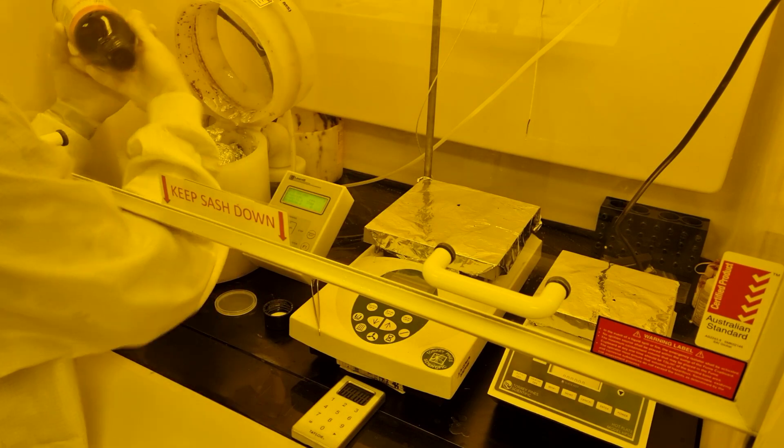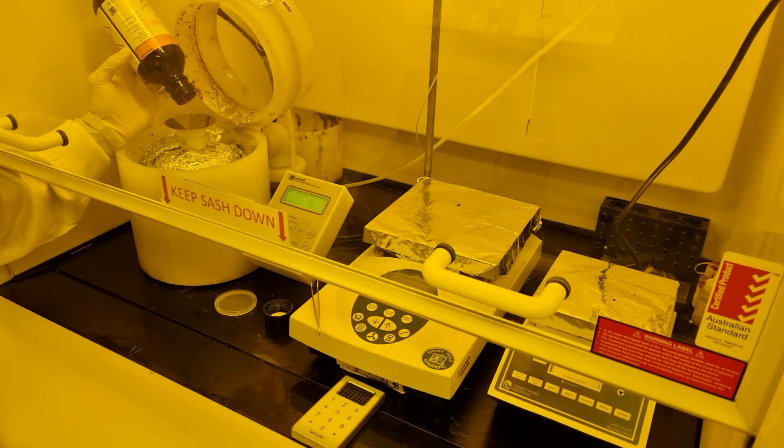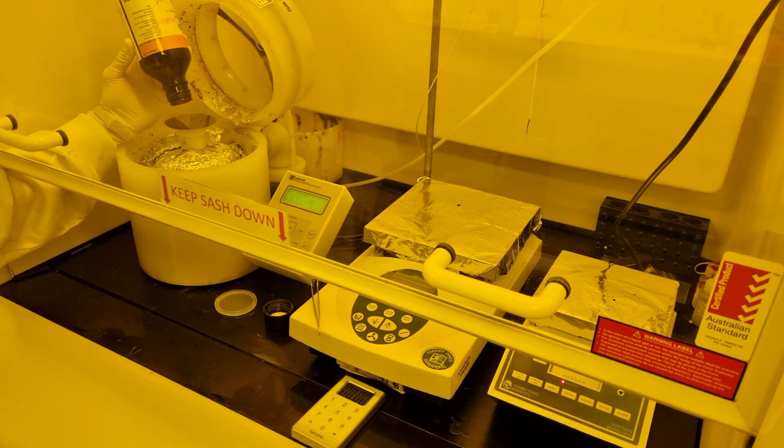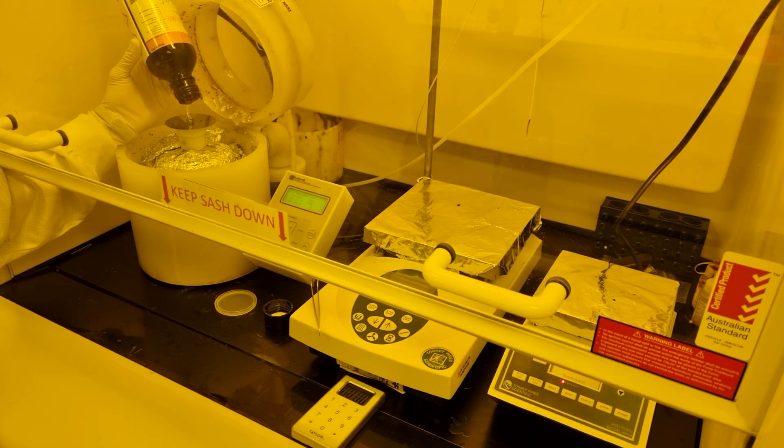The photoresist that we're using here is very thick and the bottle is almost empty, so I'm holding it nearly vertical and this bit has been sped up. You want the puddle to be in the middle and to cover about one quarter of the wafer radius. Photoresist is very expensive, so it's worth trying to use just enough, though I've actually used a little more than necessary here.